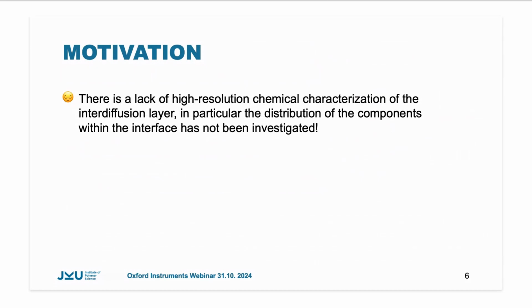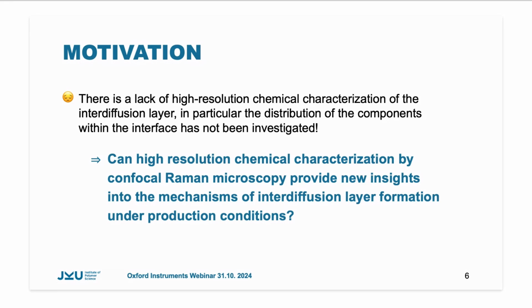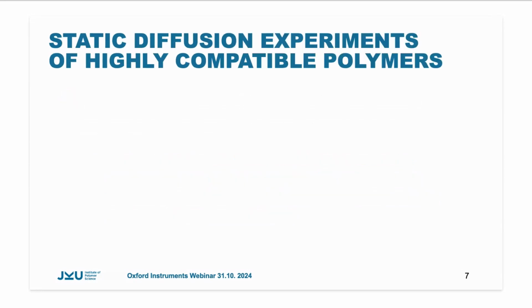This is especially because there is a lack of knowledge in high-resolution chemical characterization of the interdiffusion layer. In particular, the distribution of the components within the interface has not been carefully investigated. And this is why we thought maybe high-resolution chemical characterization by confocal Raman microscopy can provide new insights into the mechanism of interdiffusion layer formation under production conditions. Our first aim is to prove that confocal Raman microscopy is suitable to study the interdiffusion layer.